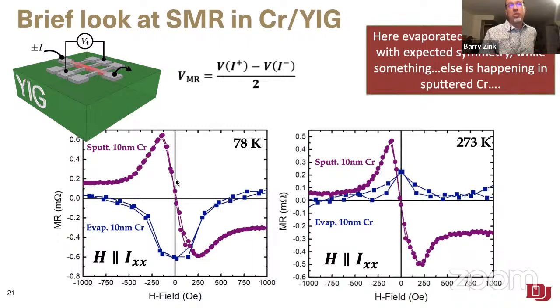But in the sputtered chromium, we see this really weird signal that has a very different symmetry than you expect from a magnetoresistance effect. So again, we're still trying to understand this. I'm mostly putting this here in case somebody has seen the exact same thing before and can just explain it to me so I don't have to think about it very hard. But there are already some interesting changes happening. Again, the sputtered and the evaporated are very different. And if you notice, the evaporated signal has a sign change from above the 200 Kelvin temperature to below it. So even though the symmetry of the signals looks kind of weird to start off with, there is stuff here that is already corroborating our story of what's happening in these chromium films. More on that to come as we understand it better.